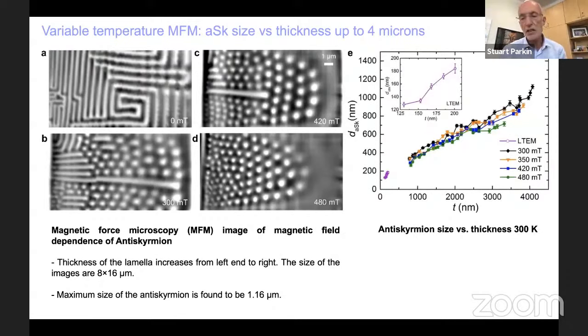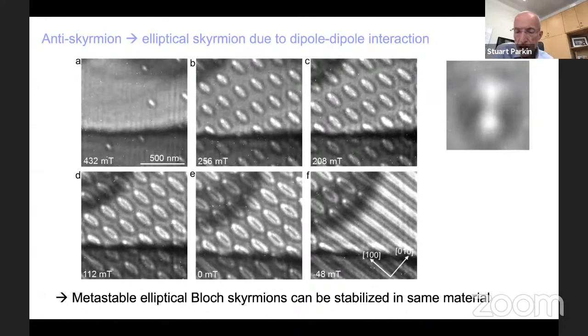So why is this? This result is totally due to dipole fields. The dipole energy completely dominates these thicker layers, the thickness dependence. And we can explain this thickness dependence from the role of the magnetostatic long-range dipole fields. This is what I wanted to say about the antiskyrmions. So they have distinct properties from skyrmions. They're more stable, they're independent of thickness, but their size can be tuned by thickness, making them technologically extremely interesting for this purpose. And I just wanted to mention, nowadays, there's a whole zoology of skyrmions.